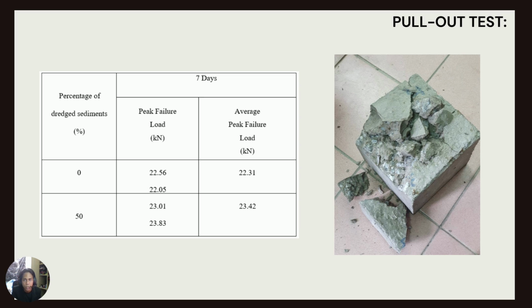Lastly, for the pull-out test, the specimens were subjected to the pull-out test for failure at the early age of 7 days and 28 days. As shown in the table, the peak failure load for dredged sediment concrete obtained is 23.42 kN, while conventional concrete obtained 22.31 kN. This shows that the dredged sediment concrete has a higher load-withstanding capacity compared to the conventional concrete. However, this test could not be completed yet because the result for 28 days of curing is expected to be obtained on 26 January and will be recorded afterwards.